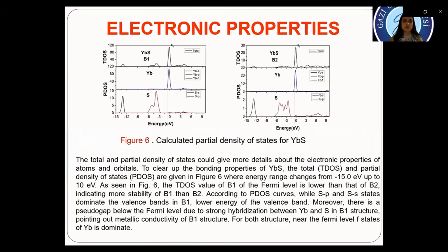The total and partial density of states could give more details about the electronic properties of atoms and orbitals. To clear up the bonding properties of ytterbium sulfide, the total and partial density of states are given in figure 6 for an energy range from minus 15 electron volts up to 10 electron volts. As seen in figure 6, the total DOS value of B1 at the Fermi level is lower than that of B2, indicating B1 is more stable than B2.